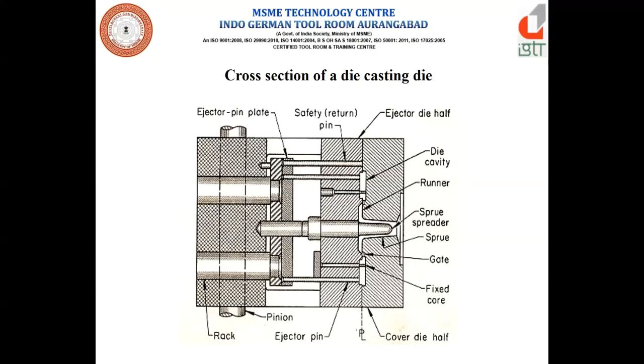This is sufficiently large to allow the escape of air and yet, under normal injection pressure, restricted enough to prevent the passage of molten metal. Ejector pins are often used for venting by grinding flats. They have to be short enough to remain self-cleaning.